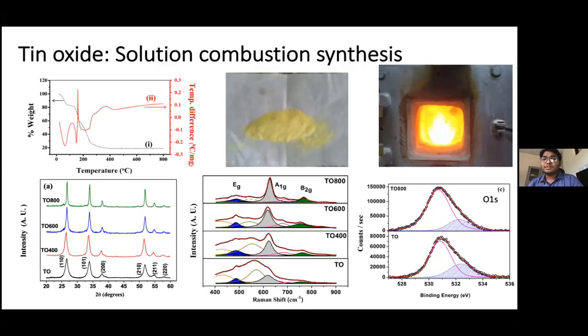So then we started tracing what could be the reason, and I started reading the literature. I would present the story this way. This material was actually made by a method called solution combustion synthesis. The name itself says it's a combustion synthesis. It's a really exothermic process. You can see the fire here. It burns off with fire during the synthesis. Momentarily, very high temperatures are reached during the synthesis, around 1500 degrees C or something like that. And suddenly that flame goes off when the fuel runs out after a few seconds. It just cools down to room temperature, or let's say very low temperatures, near room temperature.